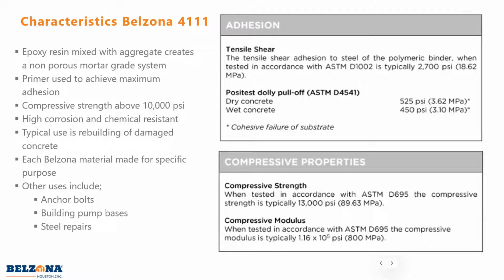Also, you'll notice our pull-offs that we have there, dry and wet concrete. So this can be applied to damp concrete, just won't get as much performance, but it still can be applied if it's damp. But you'll notice the lower numbers on the right. The reason they're that low is because the concrete actually broke, as you saw in the video on these dolly pull-off tests. Typically, it's much greater than that if we try to do it on a metal or something with better prep that can hold up to the pulls.